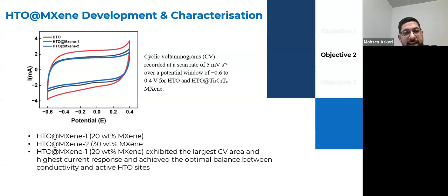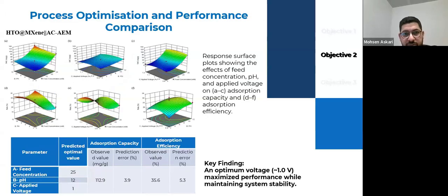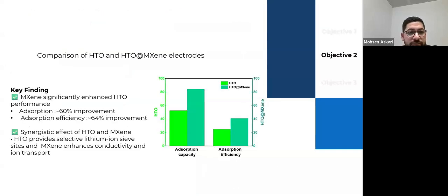So we selected the HTO and MXene 80 to 20% of each as a composite for our next experiment. First, we studied the effect of operational parameters of the CDI: feed concentration, pH, and applied voltage, presented in my CA2 in detail. The key finding here was the applied voltage. In my previous study on MXene, I found increasing the MXene increased the adsorption capacity, but here there is an optimum, and it should be an optimum voltage to have the highest adsorption capacity and adsorption rate.